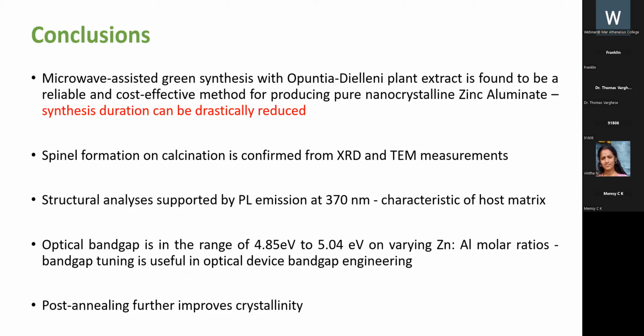And these are the conclusions of the present work. The present work, microwave assisted green synthesis, is found to be very reliable and cost effective for producing nanocrystalline zinc aluminate. The advantage is that the synthesis duration can be drastically reduced. And also the spinel formation on calcination at a very low temperature, that is 450 degrees Celsius, which is confirmed from XRD and TEM measurements.